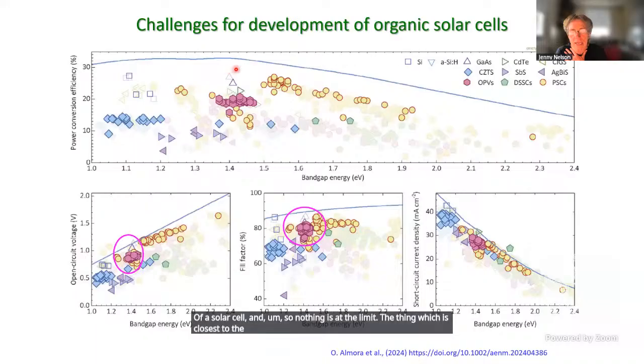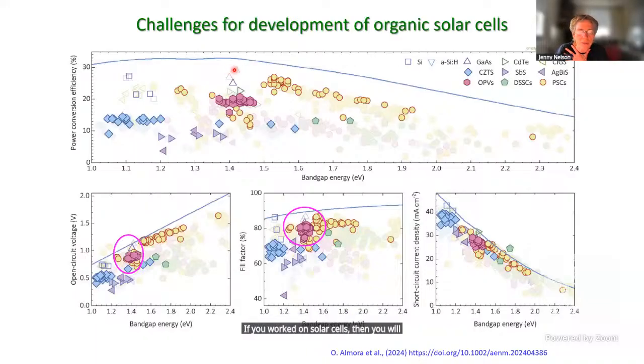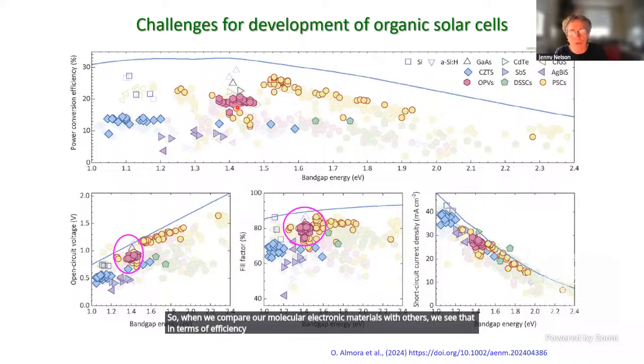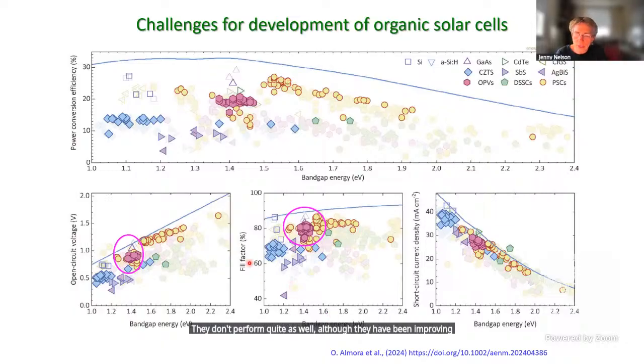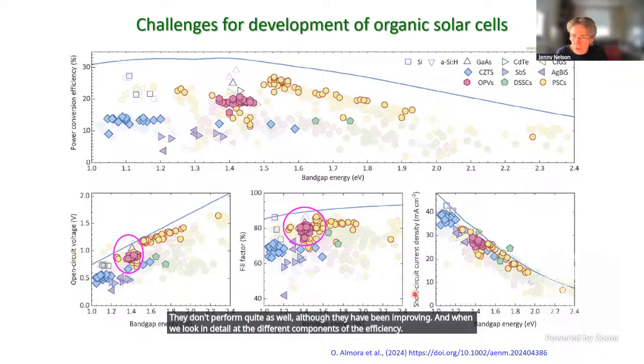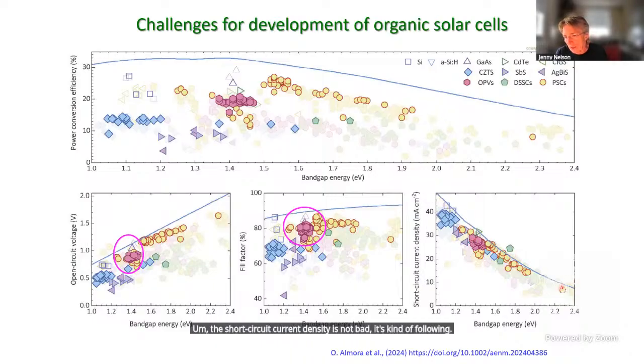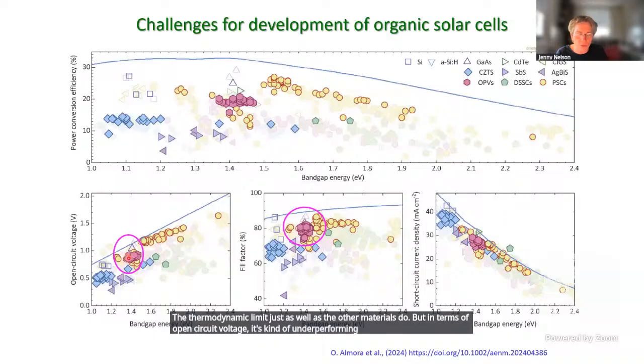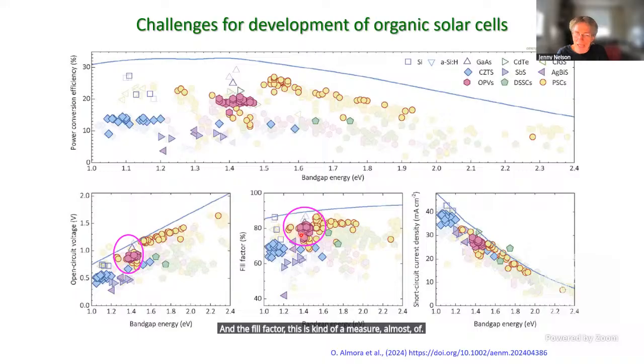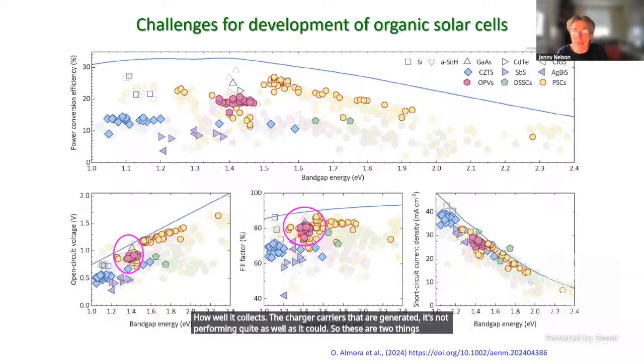The thing which is closest to the limit is gallium arsenide. If you work on solar cells, then you will probably know gallium arsenide is number one. But of course, gallium arsenide is very expensive, and it's not at the moment looking likely that gallium arsenide will scale. So when we compare our molecular electronic materials with others, we see that in terms of efficiency, they don't perform quite as well, although they have been improving. And when we look in detail at the different components of the efficiency, the short circuit current density is not bad. It's following the thermodynamic limit just as well as the other materials do. But in terms of open circuit voltage, it's underperforming. The open circuit voltage generated is not quite as good as it ought to be. And the fill factor, which is almost a measure of how well it collects the charge carriers that are generated, is not performing quite as well as it could. So these are two things which present a challenge that we would like to improve.